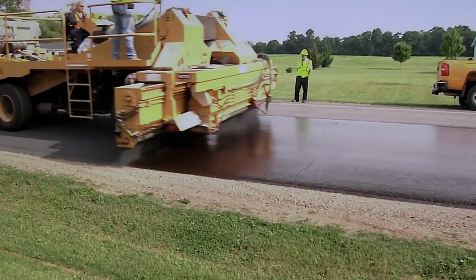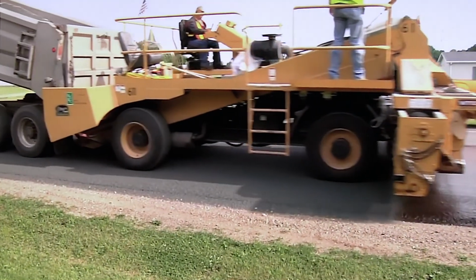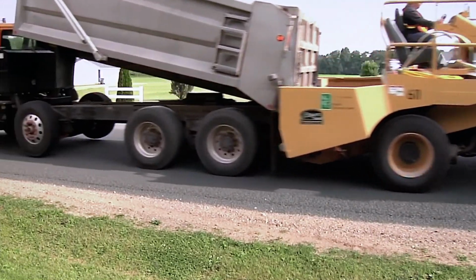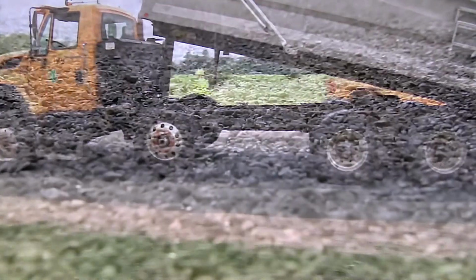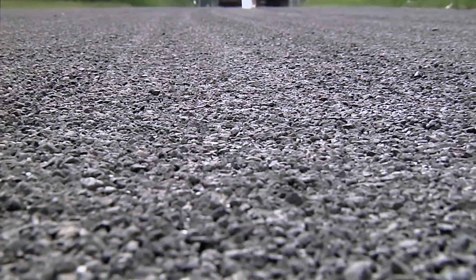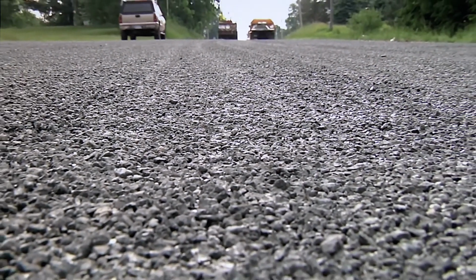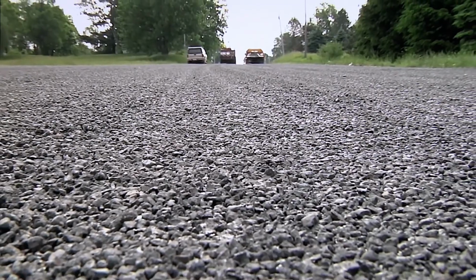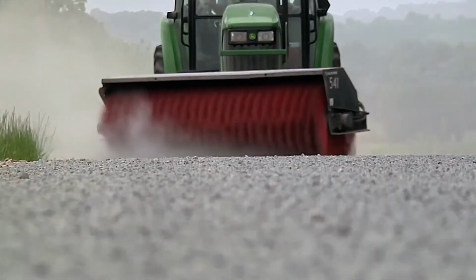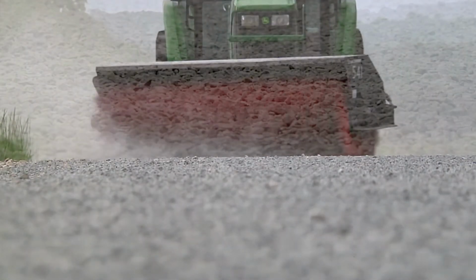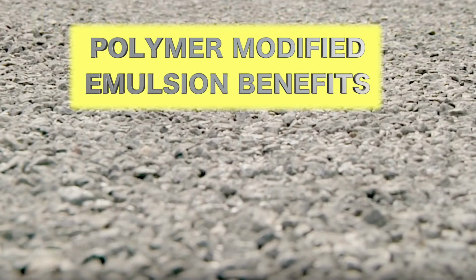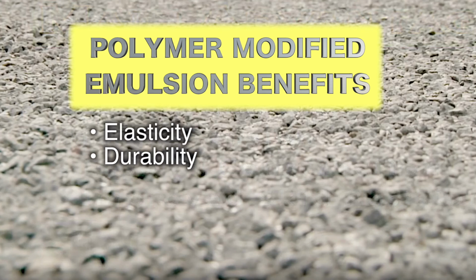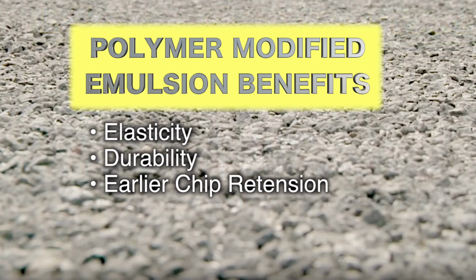HFRS2M is a polymer-modified anionic emulsified asphalt designed specifically for chip seals. HFRS2M is also a fast-set emulsion, but the total cure time is considerably longer than the CRS2P. Chip seal applications can be swept within 24 hours after application. The polymer-modified material in the asphalt emulsions provides improved elasticity, durability, and earlier chip retention than unmodified asphalt emulsions.